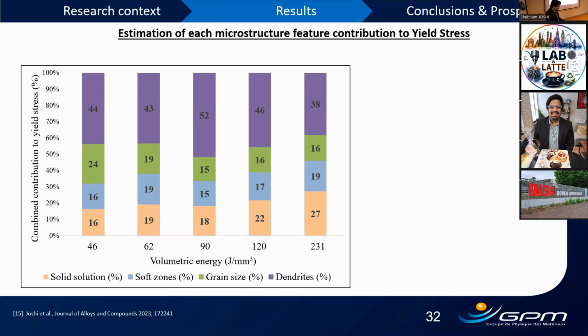So now that we are on that side, in your analysis, you have a given set of parameters that you identify or get from the literature. But I did not see in the manuscript the sensitivity analysis of each parameter, which means, okay, how wrong can I be on those parameters? How much is that going to impact this distribution? Because you have this distribution because you chose some set of parameters. But assuming we have errors or some scattering of the data, will that be very sensitive or not? I mean, would I change this distribution completely because I assume some scattering on the inputs that I'm using?